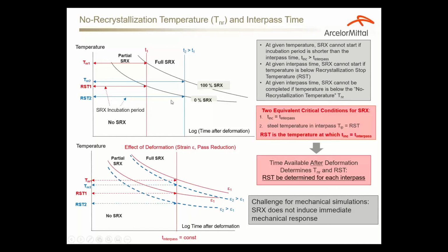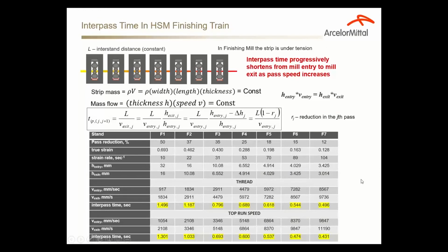So we derived 2 equivalent critical conditions for static recrystallization in the interpasses. One is when the incubation period for recrystallization is exactly equal to the interpass time, whether it's hot strip rolling or plate rolling, and when the recrystallization stop temperature is equal to the temperature of the bar in the interpasses. This is a very simple definition, but we are building, we have not finished it yet. We are building a sort of a model that allows us to predict whether or not static recrystallization occurs during rolling. As I mentioned, I'm running out of time already.